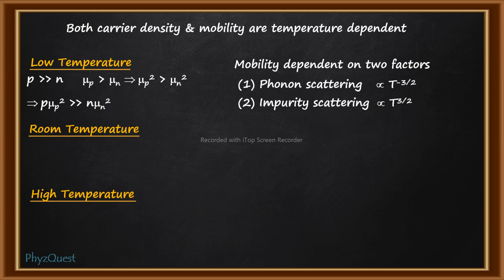Since this term p mu p square is much greater than n mu n square, the difference between them will be much higher, therefore the Hall coefficient will be very high and have a positive value. So now if we plot RH versus temperature, RH will be a high value at low temperature. Now let's talk about room temperature.